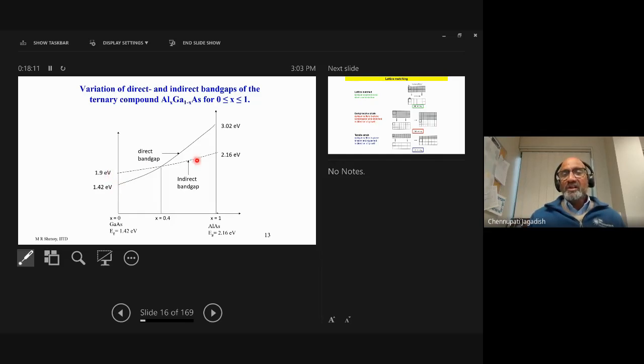I also told you that aluminum arsenide is an indirect band gap semiconductor, so that means the minimum in the conduction band takes place at a different wave vector than the top of the valence band. So while you're mixing up to a certain point of aluminum gallium arsenide, about 40% or so, you keep this semiconductor direct, and afterwards it becomes indirect. So up to this point, you can use this semiconductor for light emission applications, for example, because they will all be emitting light efficiently.